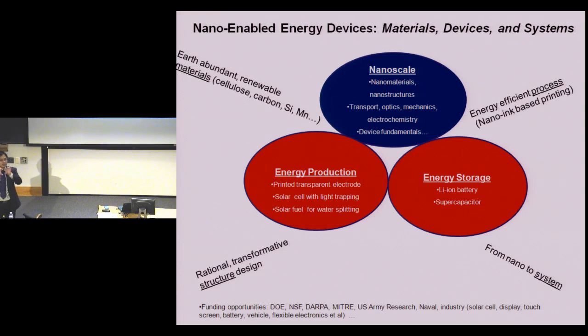But on the other side, each paper fiber is made of small fibers with a diameter of about 10 to 20 nanometers. Now, if we can disintegrate the paper, just like the way I disintegrate nanotubes, and have a perfect solution of cellulose in water, and then make a paper again from this cellulose with a diameter of 10 or 20 nanometers, the scattering of light will be dramatically decreased. That means I could get a fully transparent, biocompatible paper, and then make the paper highly conductive by using all these nanomaterials. That will allow us to fabricate next generation paper solar cells with efficient light trapping mechanisms.